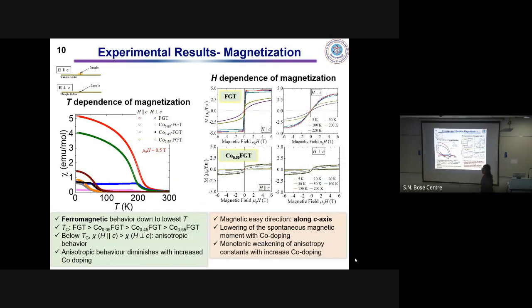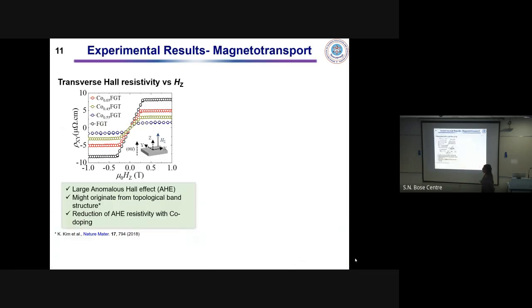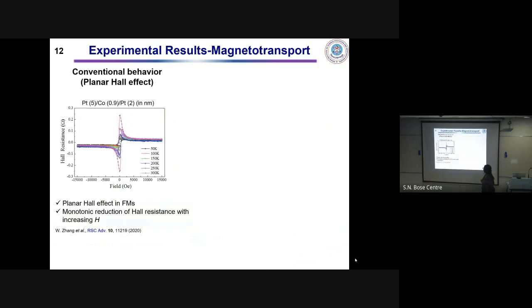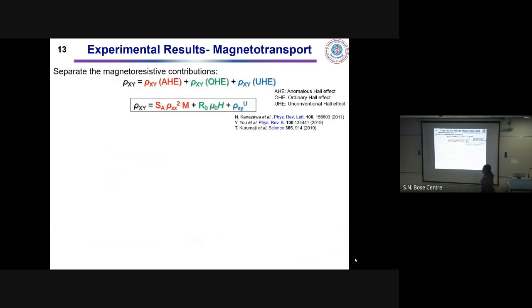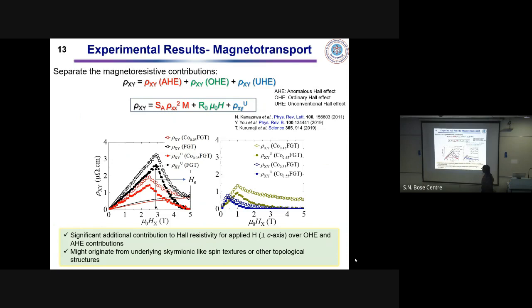How do you decouple the anomalous Hall part? Because anomalous Hall is proportional to M, right? Saturation magnetization. Yes. So you cannot decouple the anomalous Hall resistance from the equation. You just put the value of magnetization there. You can do M by H, but you cannot get the rho XY value.